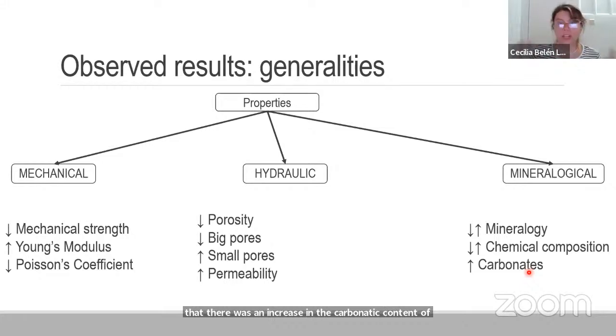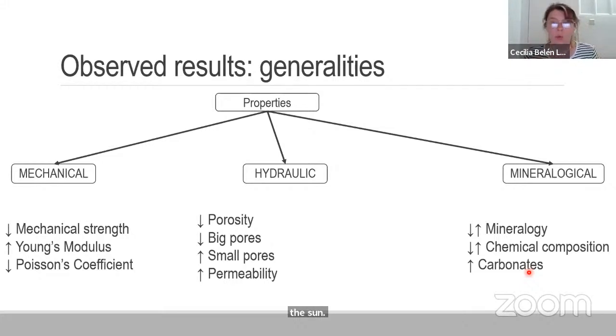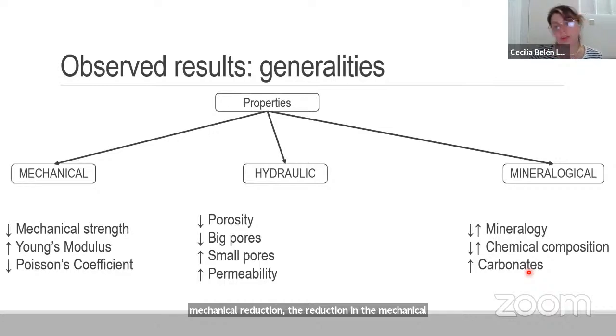All in all, we could observe that there was a reduction in mechanical strength, an increase in the Young's modulus, which meant the rock became more fragile. There was a reduction in porosity, a reduction in the amount of big pores, but an increase in small pores, an increase in permeability, and changes in the mineralogy.